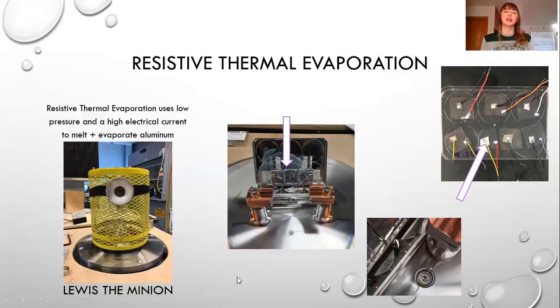And then Lewis the Minion, a resistive thermal evaporator, uses really low pressure and a high electrical current to create an environment where that aluminum in the basket can melt, and it melts so fast and so hot that it just evaporates immediately and coats everything in there, including our cells.